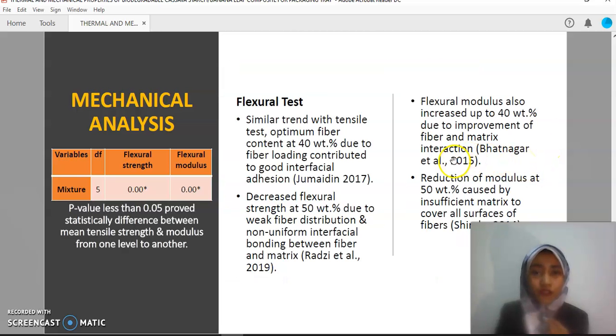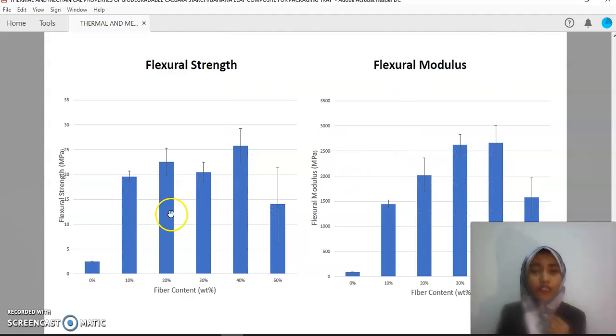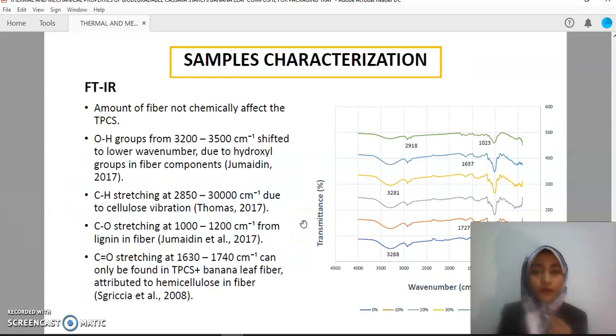And then for the flexural test, there is a similar trend with tensile, with optimum fiber at 40%, and then reduced at 50%. Why? Because higher fiber content will cause weak fiber distribution and non-uniform interfacial bonding. And the matrix is also insufficient to cover the surface of the fiber.